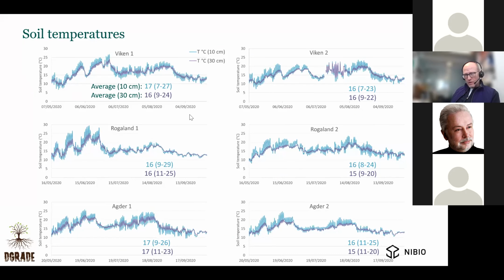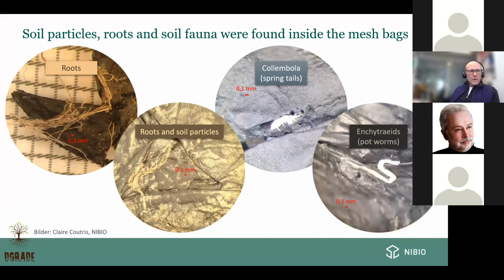Looking at the temperature at these different farms, the average temperature during the 5 months that we assessed, so the summer months, was around 15 to 17 degrees. You can see it from the different farms, different sites, pretty much the same for the three sites. When we dug these up, we could then open the mesh bags and find all these roots, bacteria, Collembola, enchytraeids, etc. These organisms, we can detect them and quantify them inside the mesh bags.